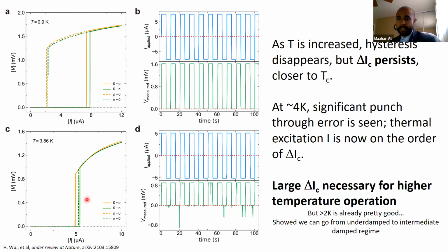The delta IC still exists though, but there's starting to be this sort of punch through error. You see the instability of the measured voltage when we flip sign. Sometimes we do see it appear to superconduct. So it's not as stable as you go up in temperature, but I think that's expected because of the magnitude of thermal fluctuation of noise current, which we'll describe in a minute. But being around 2 Kelvin, this still works just fine.